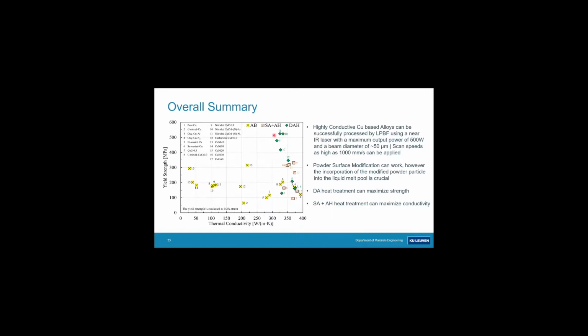So the highest strengths were always achieved with the direct aging heat treatments. That does not necessarily mean that it always had the highest conductivities, as you can see here, but the combination of both was usually better there. So in overall summary, I think Suraj managed to process a very reflective and conductive powder at very high scan speeds in a very reliable way with a near infrared laser with a maximum output power of 500 watt and a very fine beam diameter of maximum 50 micrometer. And that is for an industrial application and for somebody who wants to use this, very interesting, I think.